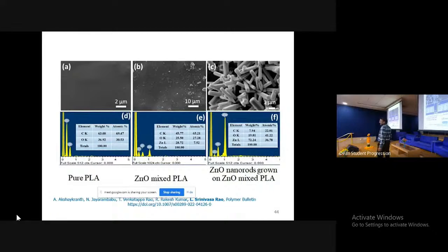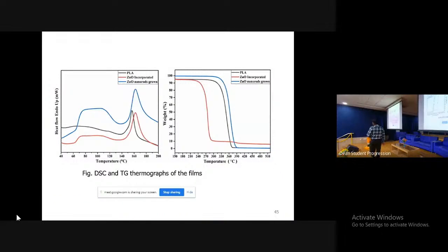And these are the nano rods developed at NIT Warangal in collaboration with Professor Dr. Srinivasa Rao sir. This is the pure PLA, polylactic acid, biofilm. We get the structure like this. After adding ZnO, we get the situation like this. We see the ZnO granules here. Later, by heating that ZnO, we have grown the nano rods like this. And we got the thermal characterization in terms of DSC and TGA also.